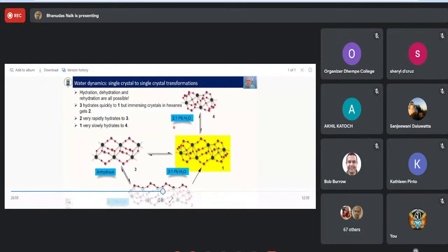This is the system we have here with 4 compounds. There's another compound, I thought there were 5 compounds, but here we go. We start with this compound, which is the first one synthesized, and it has one water molecule for every 3 lead centers. These dark spheres are the lead centers. You have one water which forms a hydrogen bonding interaction to the phosphonate ligands, as well as forming a bridge between 2 lead centers.